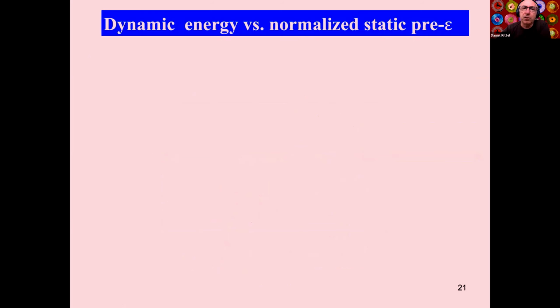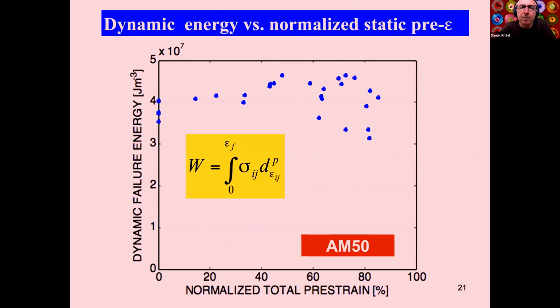So what we do here, we jump one step, and we calculate the integral of the stress strain curve in the dynamic regime only. We simply do not consider the quasi-static phase, but we plot this dynamic energy as a function of what was the quasi-static pre-strain. And here, to our great surprise, we discovered that, well, up to a reasonable extent, it's rather constant. Of course, it will fall at very large strains, but for a whole range of strains, which differs from material to material, because we have tested, of course, several materials, this energy remains constant. So that's interesting. That could be a criterion, because strain energy density is also a criterion.